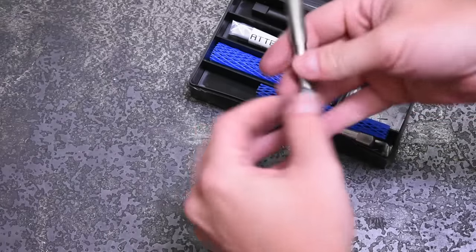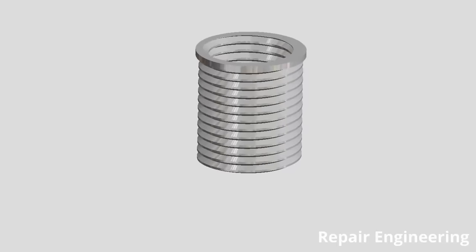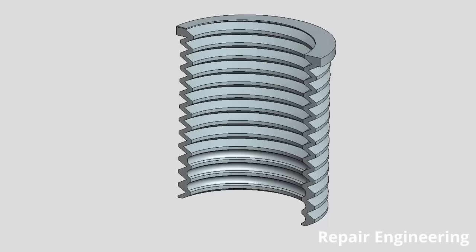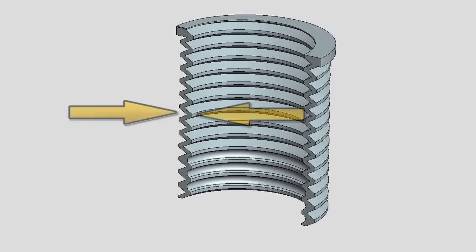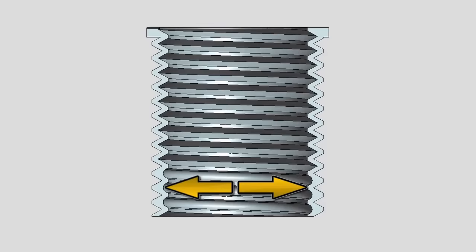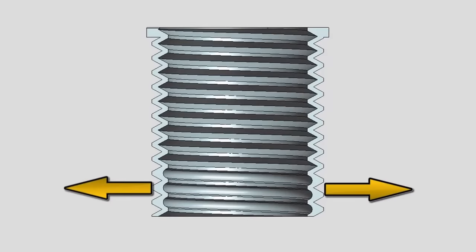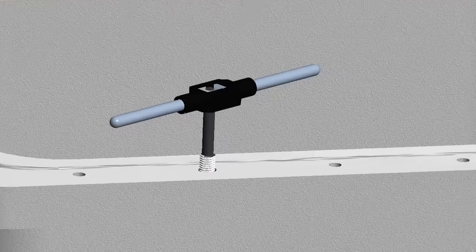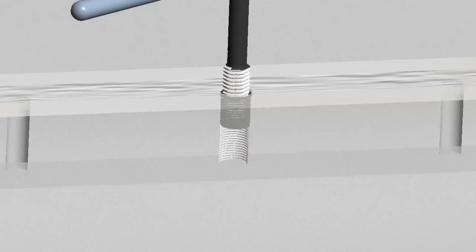These use solid inserts, which have an external and internal thread pitch that are synchronized, timed together, that's where the name comes from. The bottom few threads are underformed and get swaged in the hole by the installation tool. Maybe it's my reloading years coming through, but I can't think of a better term for that process than swaged. The threads are formed and in effect cinch up against the threaded hole, making for a tight bond.